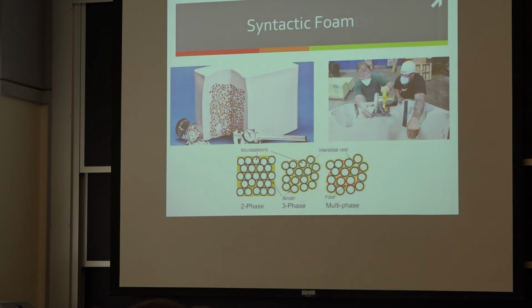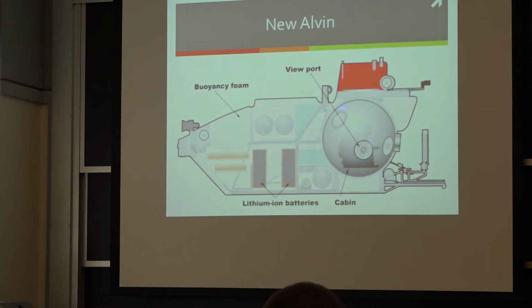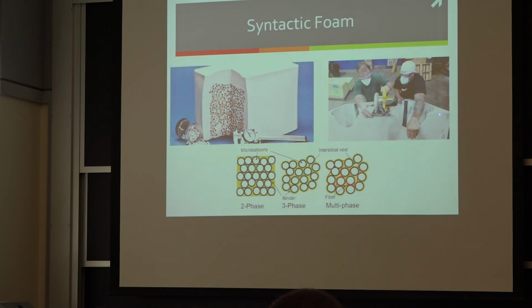So syntactic foam. Until the offshore guys started doing deep ocean work, syntactic foam was really only for these deep sea submerged vehicles. But it's little glass spheres that are packed inside a resin that hopefully will not biodegrade in the ocean and break under extremely high pressures. And it turns out they're getting this down to less than 30 pounds, less than 50% of the density of water, okay? And some of it's getting down closer to 40% of the density of water, which is great because they pack every little location with the buoyancy foam. It can be machined to any shape you want, and every available space inside that Alvin is packed with buoyancy foam, so it will float to the surface.